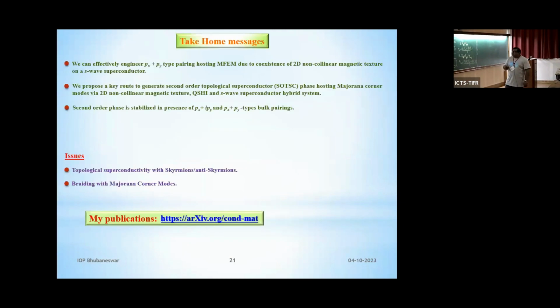Okay, so what is the take home message? So far I have tried to convince you that after one dimension, I can develop 2D topological superconductivity based on these non-collinear magnetic textures. First, I tried to show you the topological superconducting state with a Majorana flat edge mode, and based on some material support, basically manganese and niobium, I tried to show that these flat modes are quite stable and possible to realize. And in the second proposal, which is mostly theoretical, I tried to show that one can generate a second order topological superconductor hosting Majorana modes by this magnetic texture, quantum spin Hall and S-wave superconducting hybrid system.